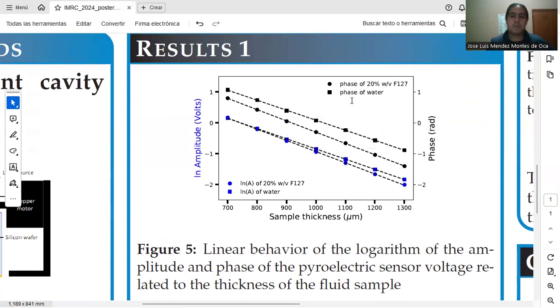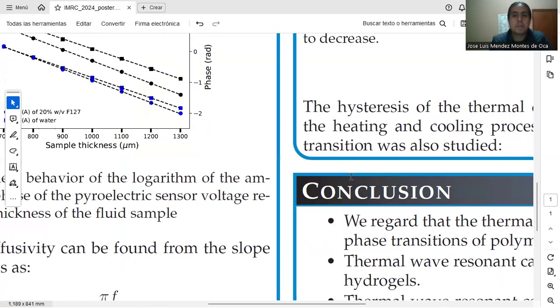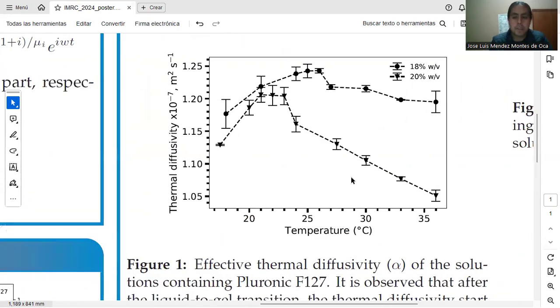Here we have the comparison between a sample with DI water, represented by the squares, and a sample with 20% of PLURONIC, represented by the circles. In this case, the percentage is weight over volume. The black color represents the signal phase, and the blue color represents the amplitude, or in this case, the logarithm of the amplitude. It is observed a small change in the slopes between these samples, and this small change in the slopes is converted into differences in the thermal diffusivities.